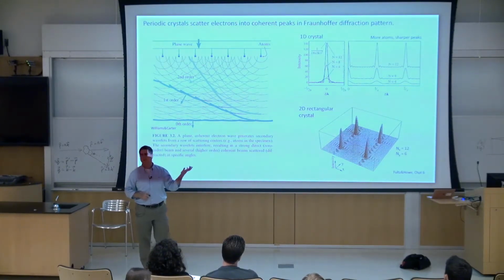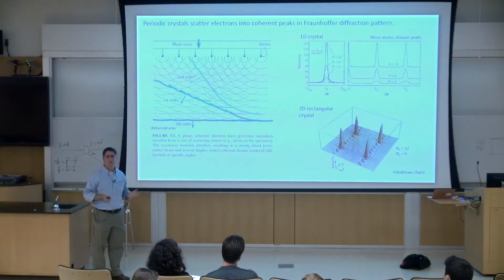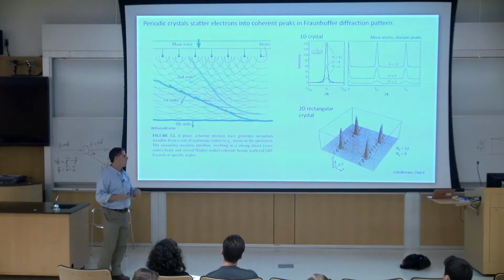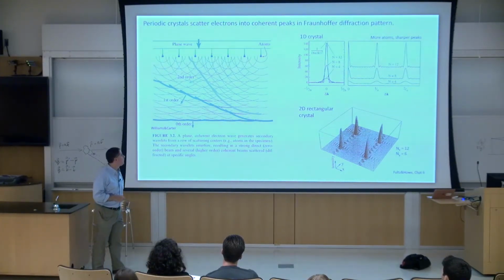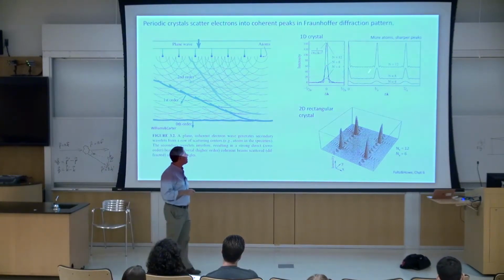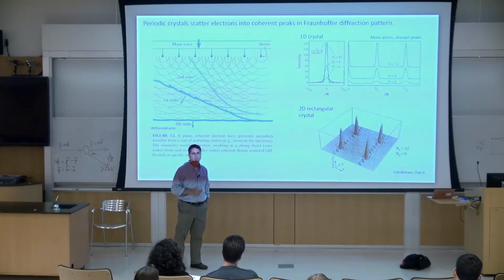So one of the things you can do with diffraction is measure the width of the peak, and 1 over the width will tell you how big the object was. Or it'll tell you how not parallel your beam was if the object gets very big. So the lesson is the diffraction spots only get sharp when you've got a whole bunch of atoms in your object.